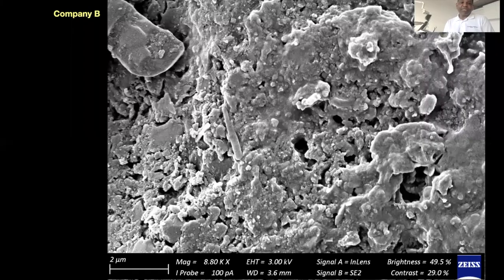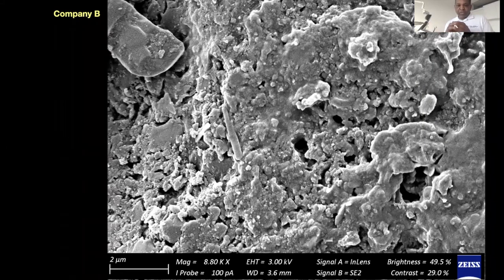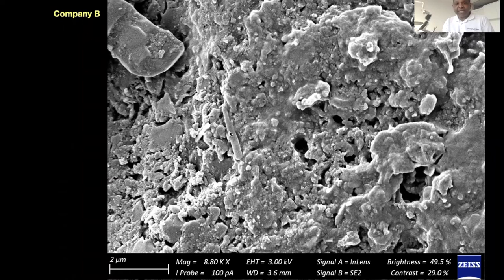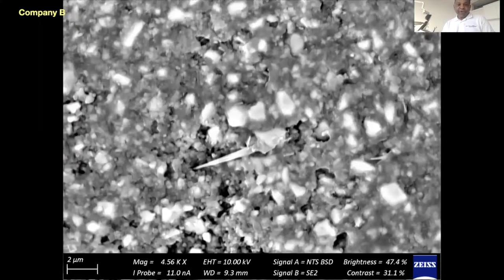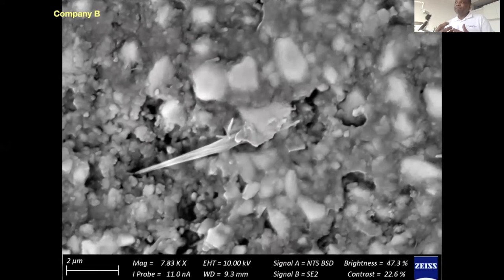Let's look at some SEMs of materials available nowadays. This is a CAD CAM block from Company B — removed from the packaging and placed directly into the scanning electron microscope. On the surface itself we found lots of irregularities, a large piece of possibly a glass particle, and lots of voids and defects. At higher magnification, a spicule of some glass type is present on the surface, along with lots of voids. Because of these voids, the restoration may eventually take up stains over time.